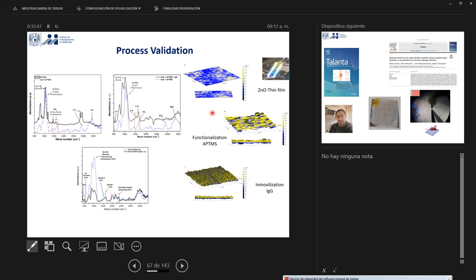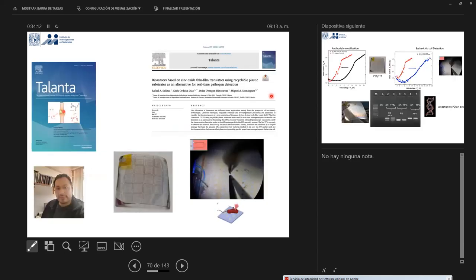Also in the AFM, atomic force microscopy, he found differences in the interaction before and after. You can see the roughness was changing. So he developed some techniques in his PhD for the detection of E. coli and salmonella, and we found that these zinc oxide thin films have potential for this kind of pathogen detection. In one of the recent works in 2022, he developed some transistors.